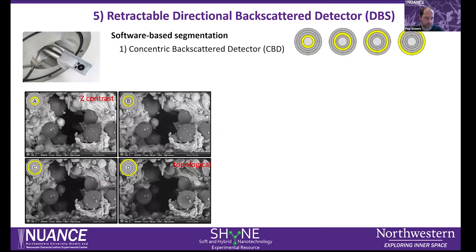The fifth detector is a retractable directional backscatter detector, which can be used in an annular fashion. You can select different areas of the detector with which you detect different signals. If you select the inner ring, you get more of a Z contrast image, versus the outer rings, you can get more of a topological type of image.